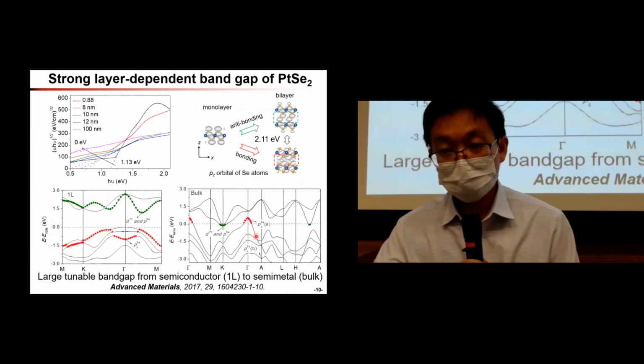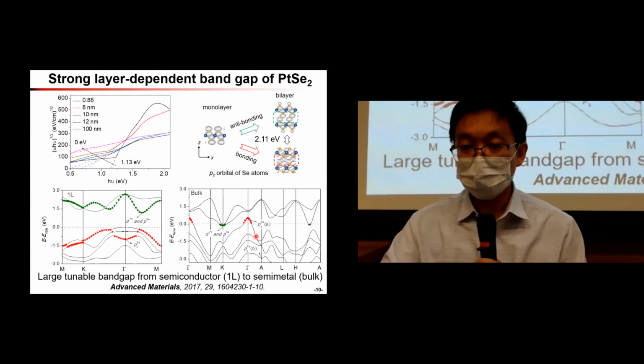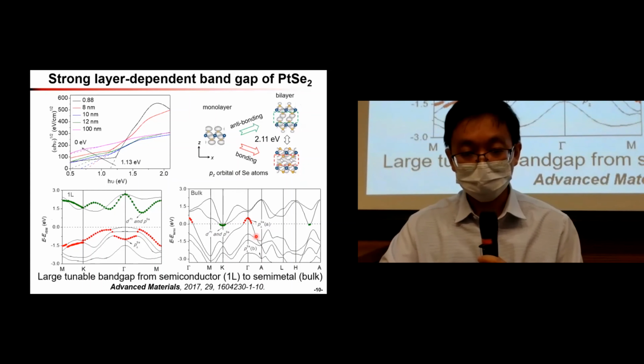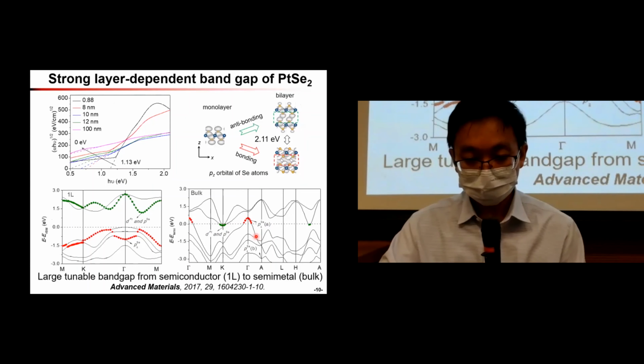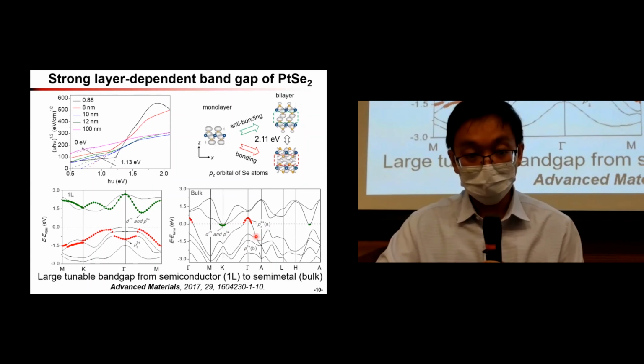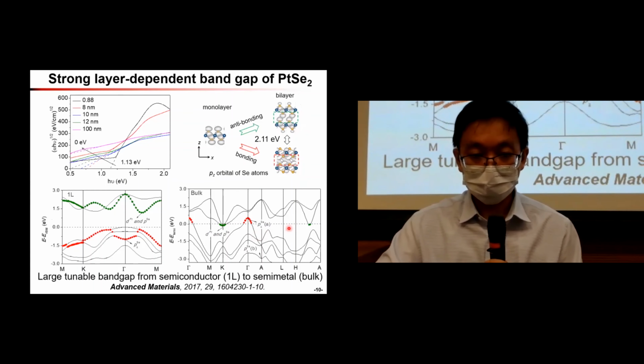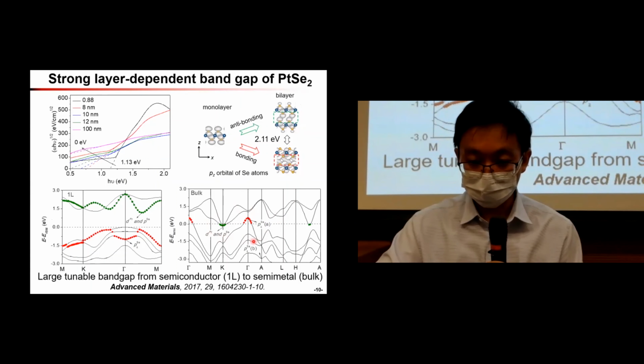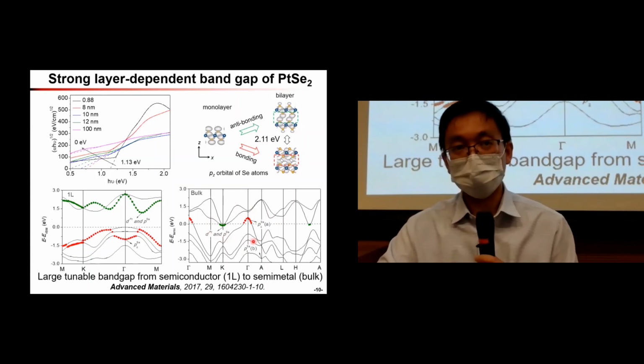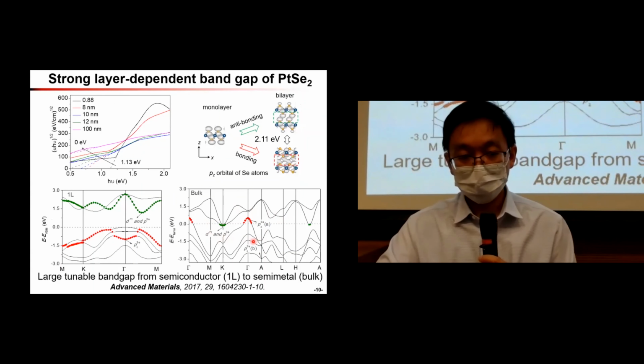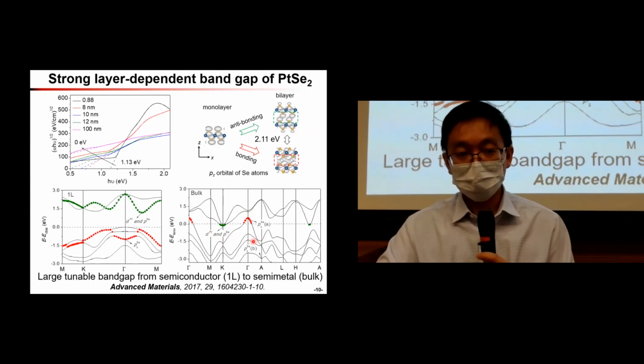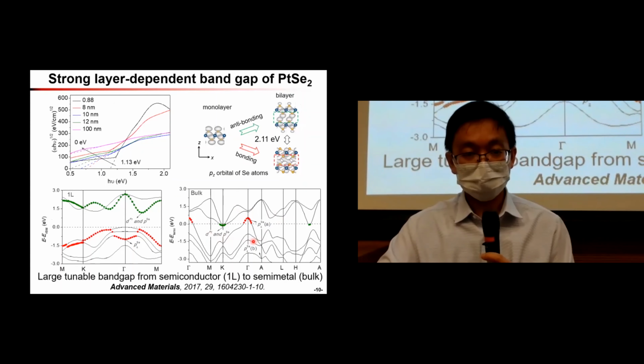For PtSe2, because the size of the Se atom is much, much larger, the interaction will be stronger. In this way, the band gap change is more significant. So from the bulk PtSe2, it changed from semiconductor to metallic. So this is the first type of material. We just change the thickness.